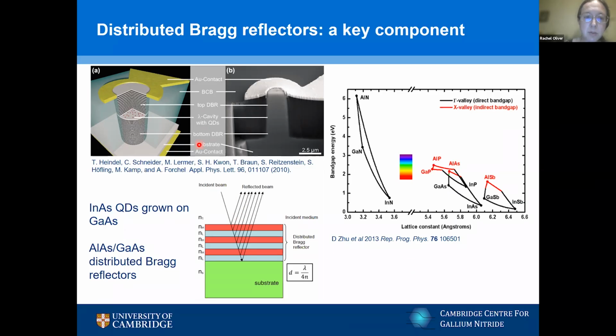If you want to make one of those in the arsenides, you use gallium arsenide and aluminium arsenide because they have almost the same lattice parameter. A lattice matched material pair. That's great, and that allows you to make great big stacks in your DBR that are unstrained, and therefore the material's growth does not deteriorate. Unfortunately, we're working in gallium nitride. So if we're talking gallium arsenide, aluminium arsenide, the equivalent would be gallium nitride, aluminium nitride, and they don't have the same lattice parameter. And that causes a lot of problems with the growth.